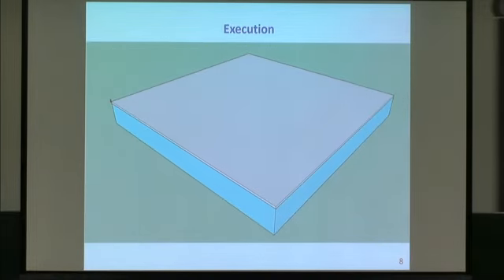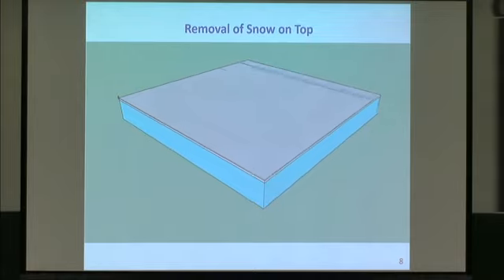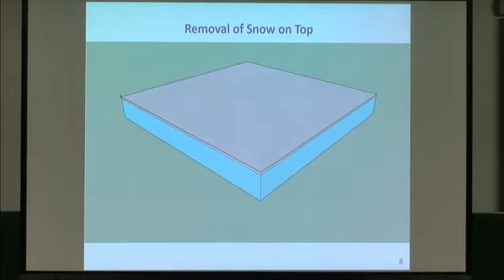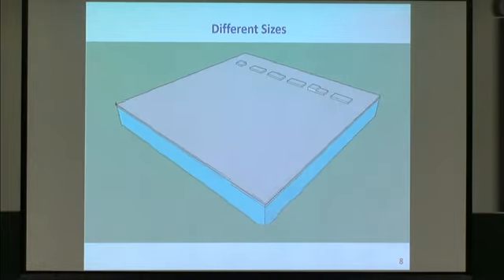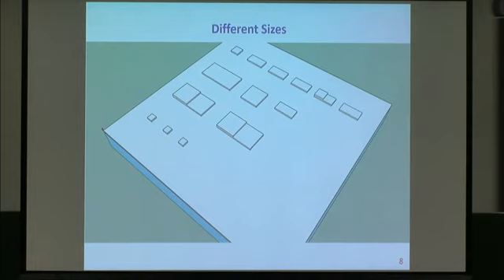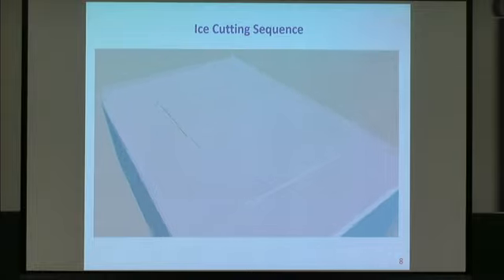So what about the execution here? Removal of snow, that's the first thing, of course. You need to have a bare surface. Different sizes, I mentioned this with the size effects if we want to study. Then also cutting sequence, as you can see here. Typically this is 5 meter in the crack direction and 10 meter wide on the other side. And as I say, it is important to have this in such a way that you can do it relatively fast.